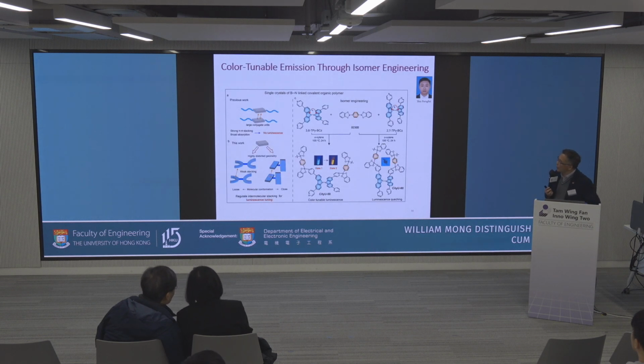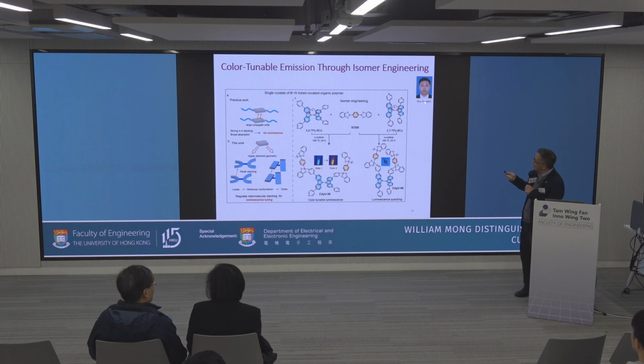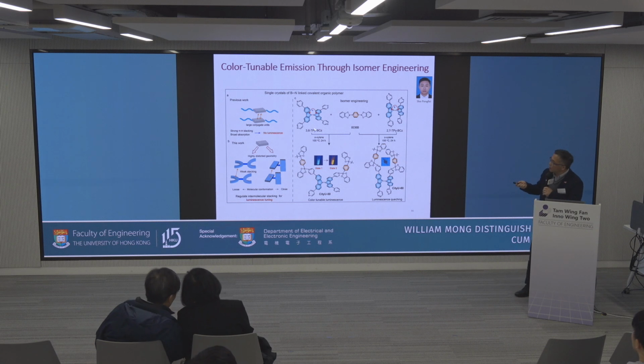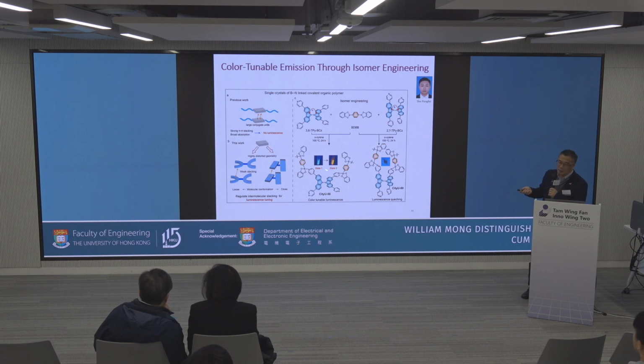And then what happened for the emission? My another PhD student and postdoc, now he actually found a factory position in China. So what did we do? He made 2 different organic building units. One is the 2-pyridine in the 3 and 6 position. Another is the 2, 4, 7 position as shown here, and then 2, 7 as shown here, and then he grew the single crystal. For the 2 crystals, for the first one, you can see we have the very nice emission. However, for the second one, almost no emission.